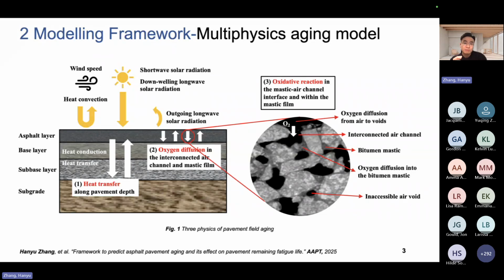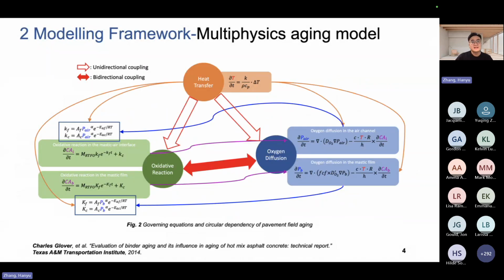So to sum up, pavement aging is a multi-physics phenomenon that is highly associated with temperature and the oxygen amount. Then after we understand the aging mechanisms, we need to formulate a series of equations so that we can model pavement aging using numerical methods. The credit here goes to Professor Charles Glover and his team at Texas A&M University for developing those coupling equations. So for our project, we developed our aging model based on their work. I would like to note that in our project, we select the carbonyl index as the aging parameter because we think it's still the most appropriate indicator for quantifying aging in terms of the current mainstream binders.